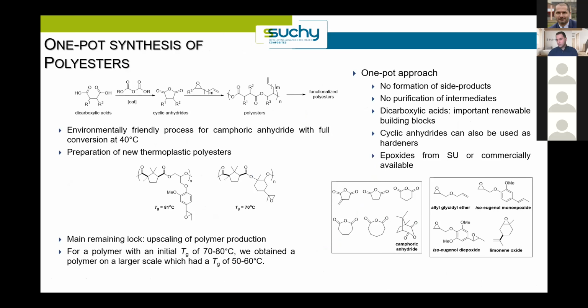For the preparation of thermoplastics, our strategy was first to evaluate the feasibility of the synthesis of new polyesters by a one-pot approach, which avoid the formation of side products and the purification of intermediates. Using this approach, we were able to prepare new thermoplastic polyesters and to obtain a green process to synthesize camphoric anhydride, which can either be used as a hardener or as a co-monomer. Thus, the two most promising thermoplastics we obtain have been prepared to form mini samples of composite dedicated also for bending test. However, the first experiment performed showed that our polymer were too brittle. So to avoid this problem, we used bio-based plasticizers, but unfortunately, we obtained a polymer on a larger scale, which has a Tg that was too low.